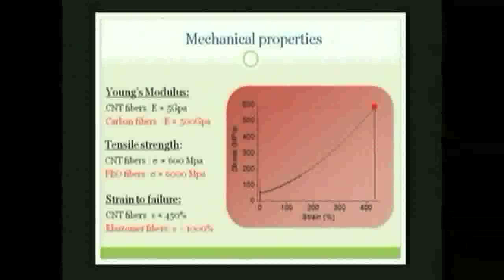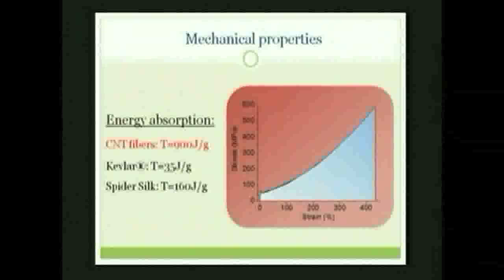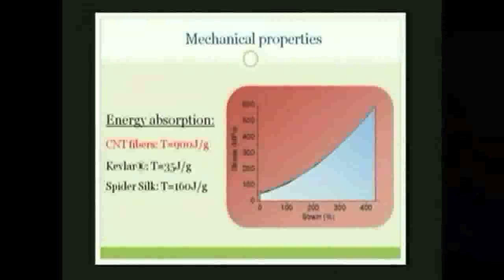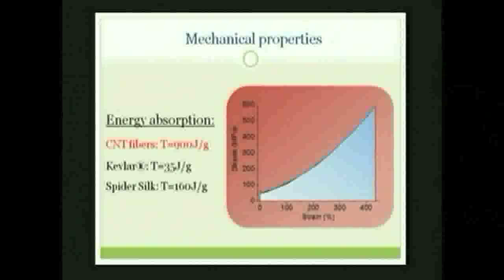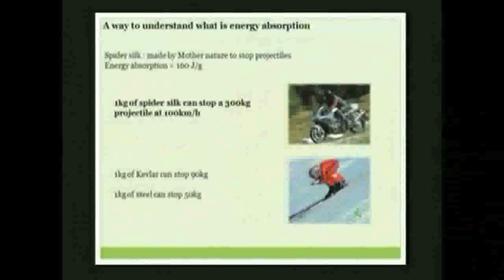In fact, this is a combination of the 3 properties which is interesting, and the combination of these 3 properties is the area under the curve. And the area under the curve is what we call the energy absorption, the quantity of energy that the fiber can take before breaking, okay? And this energy absorption is very high, it's 900 joule per gram, to be compared with Kevlar, which is an industrial synthetic fiber, which is used for this ability to absorb energy. So we are much higher, and also much higher than spider silk. But in our case, the price to pay is that the deformation rate is very high also. So the fiber will deform a lot before breaking, and this is not always suitable.